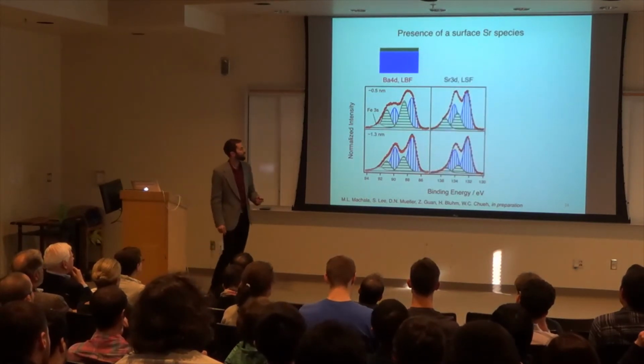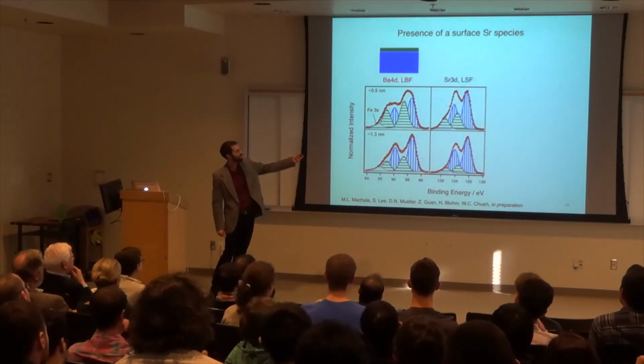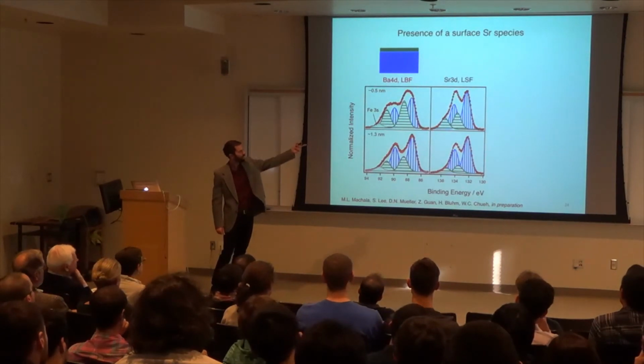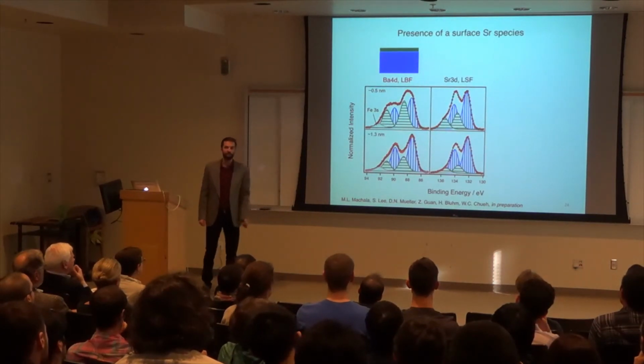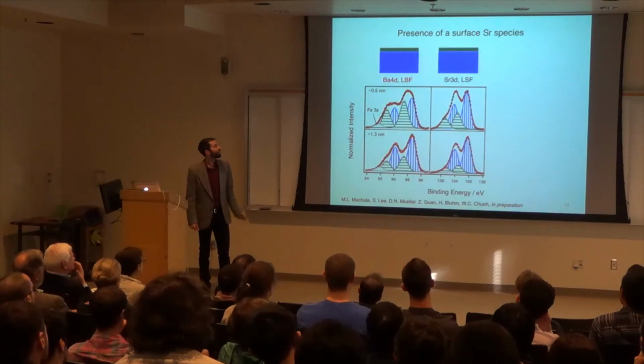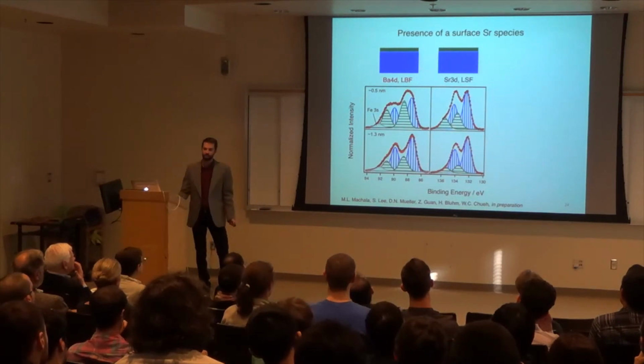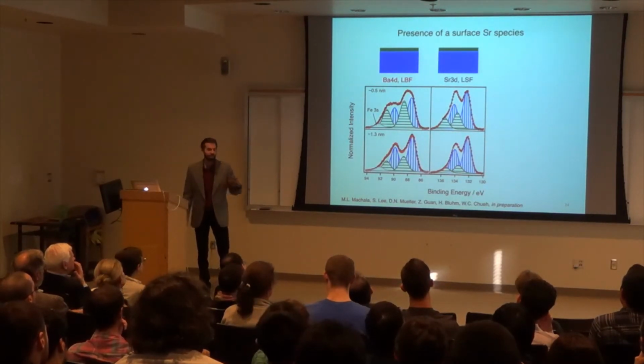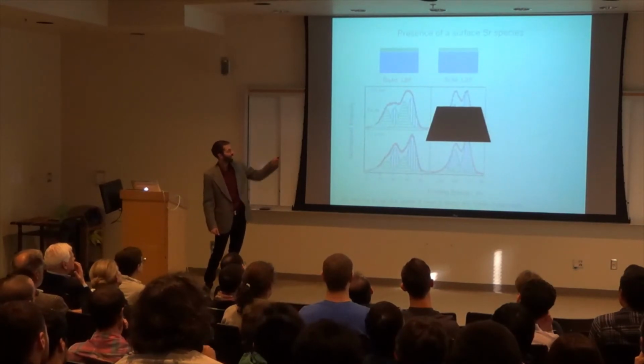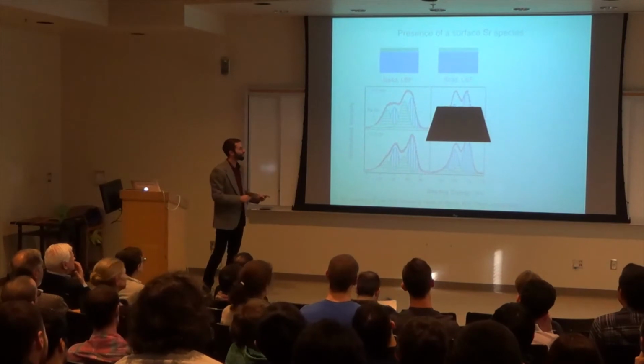Now, if we go to the strontium sample, we see a similar trend. The green relative to the blue decreases as you go deeper into the bulk. And so we also have a species found at the surface. Now what surprised us, well, you can't actually see anything here. So I'll get back to this in a little bit: what is that secondary species?